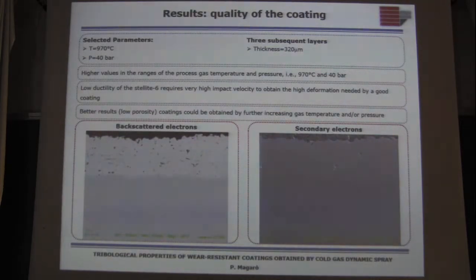On the basis of the microscopic observation, the higher values of the thermomechanical parameters investigated were selected, which suggests that maybe better results in terms of low porosity could be obtained by increasing these parameters, gas temperature and gas pressure. In fact, the low deformability of Stellite 6 requires very high impact velocity to obtain the high deformation needed for a good coating.